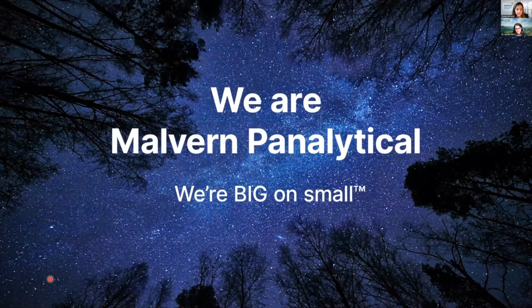Can you go into more detail on how particle size and shape is important for solid state batteries? Yes, most of the examples I was showing were the traditional liquid electrolyte batteries, but basically in any process where you're looking at packing density, flowability of materials, or reaction rates, this is where particle size and shape is going to be important. And for a solid state battery, where you've replaced the liquid electrolyte with a solid electrolyte, the particle size ratio between the active cathode material and the solid electrolyte is important. I think studies have shown that the particle size of the cathode material should be bigger than that of the solid electrolyte to give you higher energy densities.